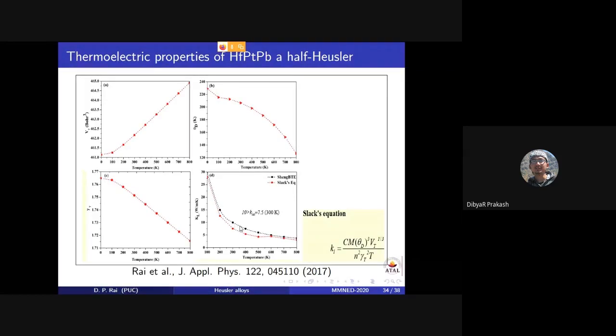By using this formula, we have calculated this KL, and our results look close to the results calculated from the ShengBTE code. ShengBTE is also a very good code for calculating the KL value, but the computational expense is very high, particularly in this kind of calculation. So we have used Slack's equation, and our results are more or less comparable with ShengBTE's results.